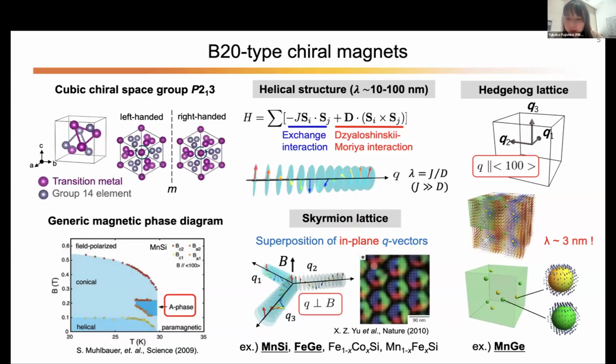This kind of skyrmion texture was first found in manganese silicide, while iron germanium, which is the target material of the second part of the talk, has a very high transition temperature near room temperature, so it has also been studied very well. On the other hand, the hedgehog spin texture is found only in manganese germanium with a very short magnetic period. I'd like to note that a very short magnetic period is very promising, because the emergent magnetic field is proportional to the density of the spin texture. This means that if the magnetic period is very short, we might have large electromagnetic responses from these topological spin textures.